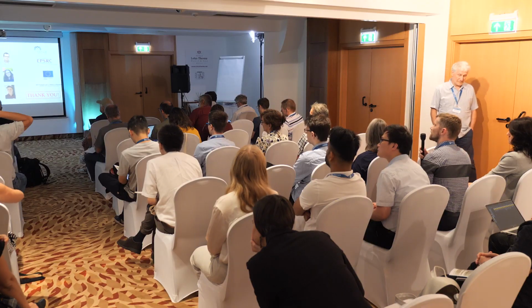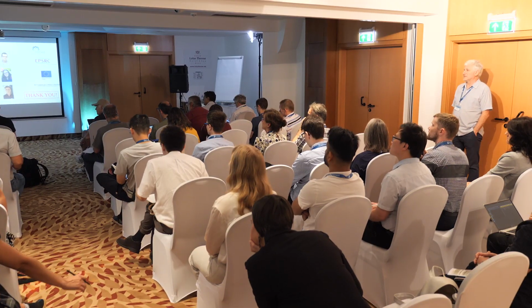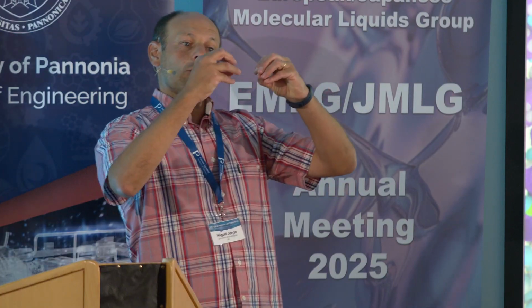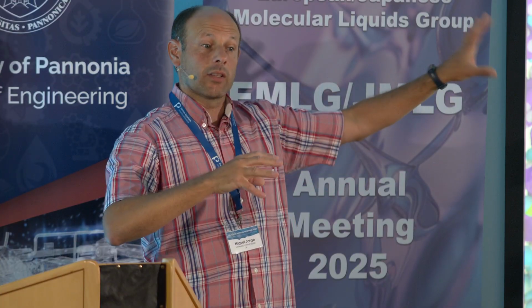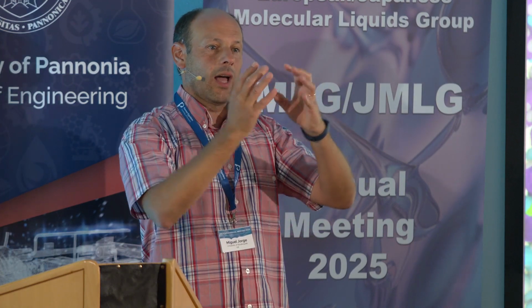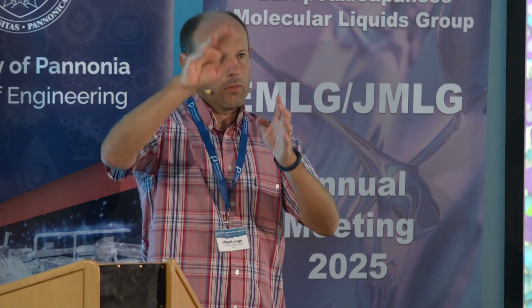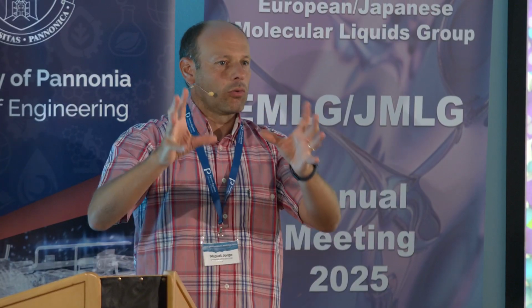And in the reactive model, what is the interaction between the patches? The sticky particles interact with other sticky particles through a very strong Lennard-Jones potential, because it's still based on the Martini, which is Lennard-Jones based. So they interact very strongly at very short distances. It has a short cutoff and a very deep well. So when they come into close contact, they will attract, and if they're far apart, they won't.